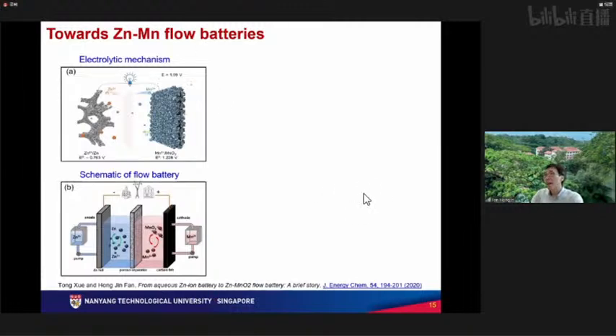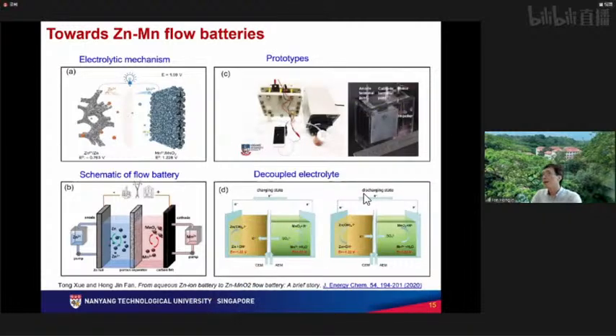So if on both sides you just put current collectors without any active materials pre-deposited on them, and just put the active material in a solution, zinc sulfate, manganese sulfate, then you can have a redeposition and dissolution process on both sides. So basically that's the concept of the flow batteries. But actually, commercialization of flow batteries has a lot of problems, especially in terms of the cost, the efficiency, and the dangerous issues on the zinc side. So there's still a lot of work, right? But still, there are some very promising prototypes.